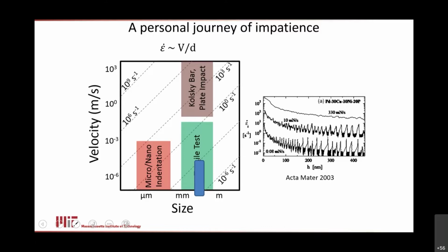So instead of conducting one test over the period of weeks, I might do thousands of tests in a period of weeks. So I could really generate a lot of data. And TG and I were also interested in doing high strain rate work. And so we pushed nano indentation up to really its limits, which was maybe 10 to the 2 per second as a strain rate. And we could study things like the transition from serrated flow to smooth flow in this metallic glass type sample. Nano indentation has a natural strain rate that's on the order of 1 per second, and we really pushed that as much as we could.